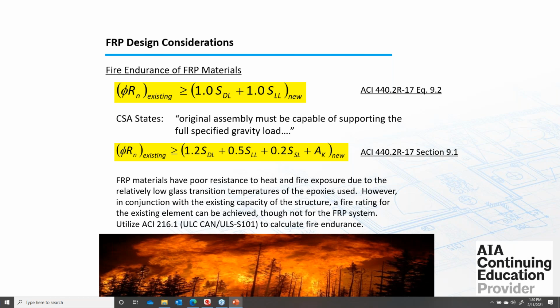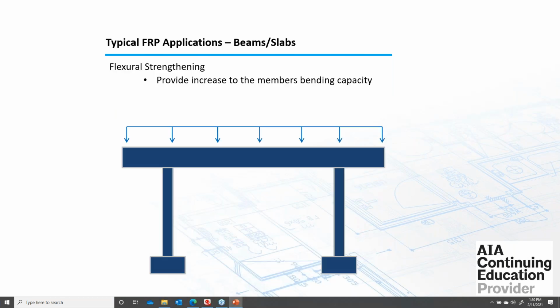If it can't carry the loads, if you're in a collapse situation before you put the FRP on, you should not be using FRP, because there's no way to fire protect FRP. You can maintain fire ratings and use FRP, but you can't actually fire protect the FRP. It's going to burn and be lost generally in about 10 to 15 minutes in the event of a fire. So both the CSA and the ACI guidelines address that and prevent you from using FRP in situations where it would be required as a primary load carrying member.